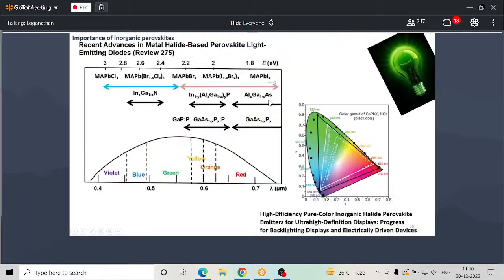So it's quite important. And here we can see there are different kinds of perovskites they use. In the past, whatever inorganic-based materials they used, they could not tune the color. Here, with one material, if you tune a single component, you can end up with different colors. That's quite exciting. You'll get violet, blue, green, yellow, orange, red. You can easily tune your system just by tuning your halide components. In this case, you can see MAPbCl3. If you substitute Cl with bromine, you'll change your color easily. So if you tune your halide concentration, your stoichiometry, then you'll easily get different colors. So it's quite exciting to work on perovskites.